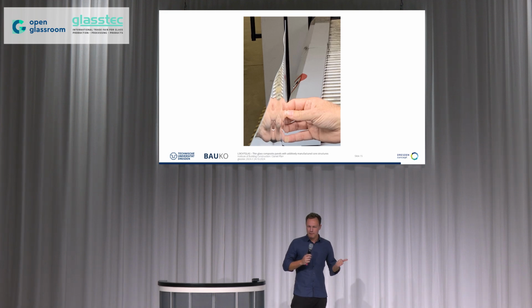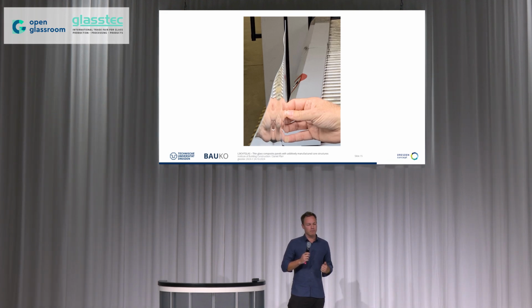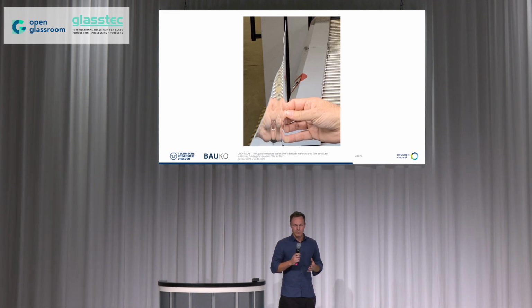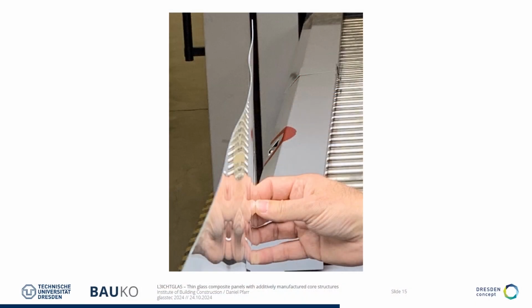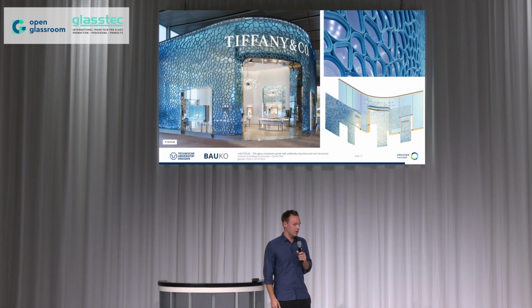Well, of course, we have some challenges to overcome, for example, in the thermal tempering process. So this was a picture made by our project partners where we have tried to thermal temper a 0.7 thin glass, and you can see the thermal distortion because of the thermal expansion of the glass coming out of the oven. Sometimes the glass flies away in the oven and so on. So there's still a lot to do.